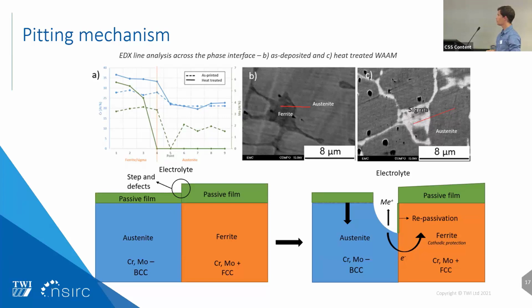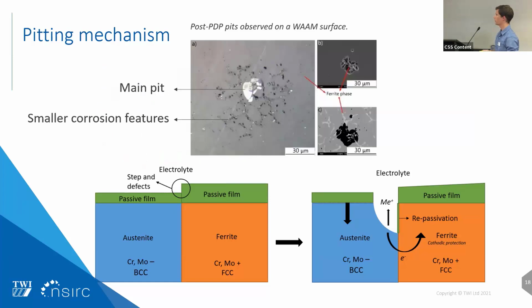Now, we couldn't find any clear evidence of a chromium depletion zone, so it is still unclear whether this happens, and that would be preferential breakdown of the passive film at the boundary between the two phases. It is still to be determined, and I will talk a bit more about this in the future experiments.